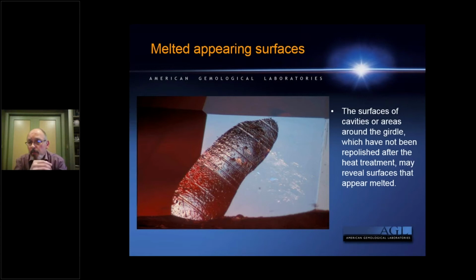So here's another practical kind of thing that I wanted to show people. When you're looking at a stone for whether it's heated, don't forget to look at the surface. You can use reflected light, because sometimes the inclusions, even sometimes spectroscopic data, may not give you enough information. But there may be areas, whether it's cavities or areas on the surface which they forgot to repolish after the treatment process, that show evidence of heating.